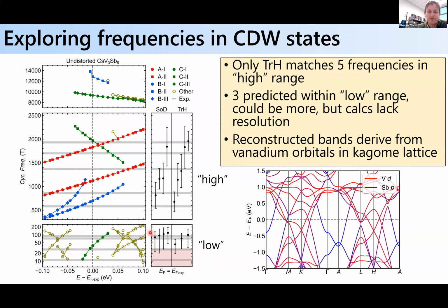Then we can calculate what frequencies would be expected in the Star of David and trihexagonal structures, which are shown here. The shaded box at the bottom is the resolution of the calculation that Sam's doing, meaning he can't identify orbits from his unfolded band structures below this frequency threshold. If we do that, then only the trihexagonal state really matches the 5 frequencies in the high frequency regime. Both the Star of David and trihexagonal do predict additional frequencies in the low frequency regime, but only the trihexagonal matches in the high frequency regime. So that model is the only one that's qualitatively consistent with the quantum oscillation data.